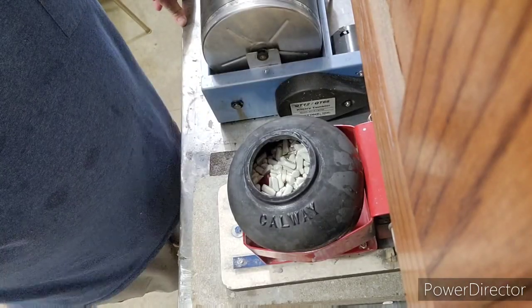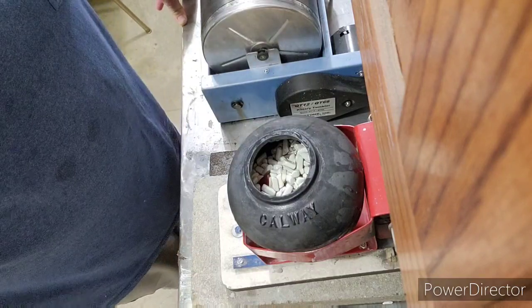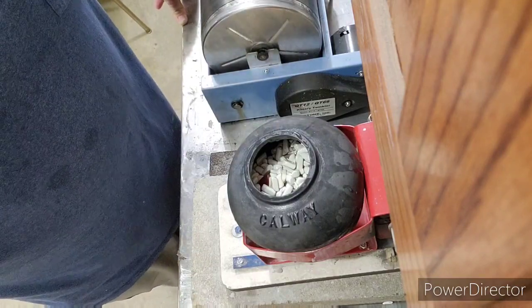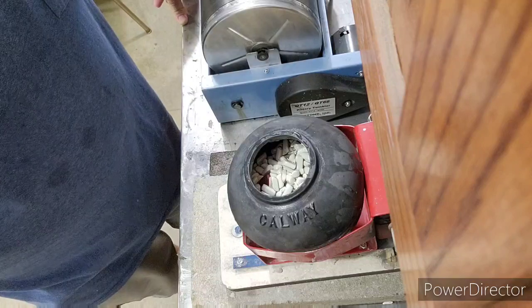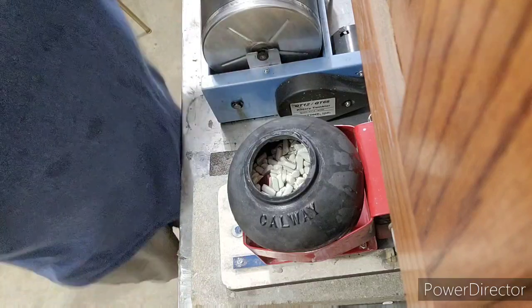All right, they went for 2 days in the 500 grit silicon carbide, and now we're ready to move on to 1000 grit silicon carbide. So it'll be a half a teaspoon of the grit and 1 tablespoon of the borax, and we'll go for another 2 days.